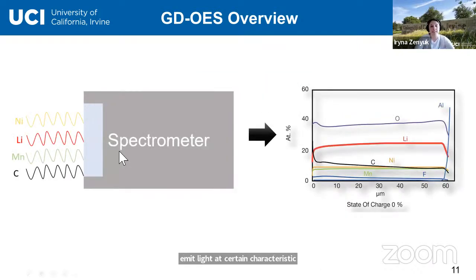This characteristic wavelength is then detected by a spectrometer, and this way we can detect all the elements that are present in this interface and in the bulk material of the cathode or the anode or the combined battery, for example. This is an example showing state of charge of 0 of the battery. So the battery is fully discharged, and you can look at the distribution of the elements in the cathode of a standard NMC type of electrode. Once we sputter away the full thickness, we reach the aluminum current collector. What's interesting here is that we can detect interfaces which are nanometer size, because we can really slow the process down and resolve species spatially through these nanometer domains, and then sputter away into the thickness of the electrode and detect all the other bulk elements.